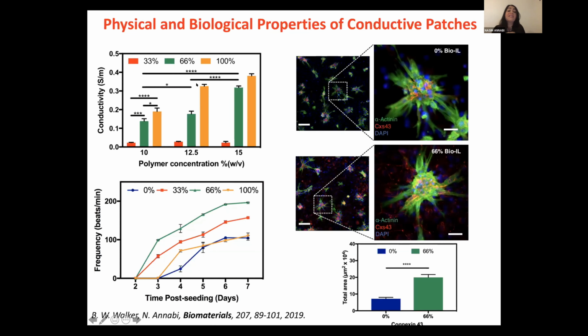We formed this substrate, we selected some formulations of that, and then we cultured cardiomyocytes on the surface of them, and then we measured the beat frequency of the cells over time. And if you look at this figure, you see that the cells respond to the level of the conductivity in the biomaterial. The blue line is the material with zero bio-IL. It is non-conductive scaffold. And the yellow line is the material formed with the highest level of conductivity. And you see that the beating frequency for both of them is lower compared to the formulation that has medium concentration of bioionic liquid.